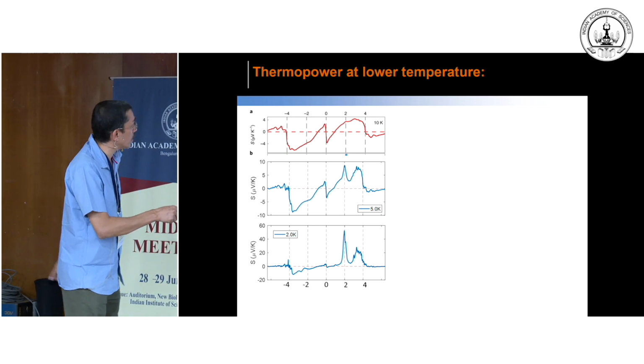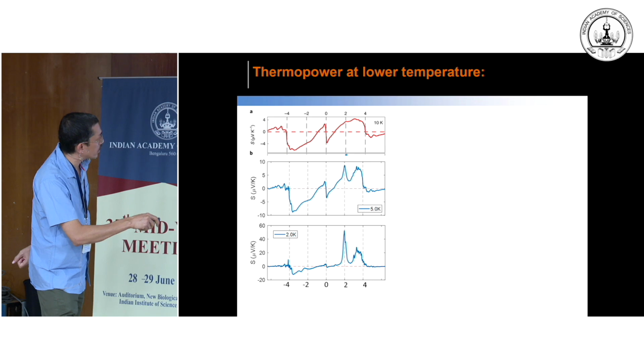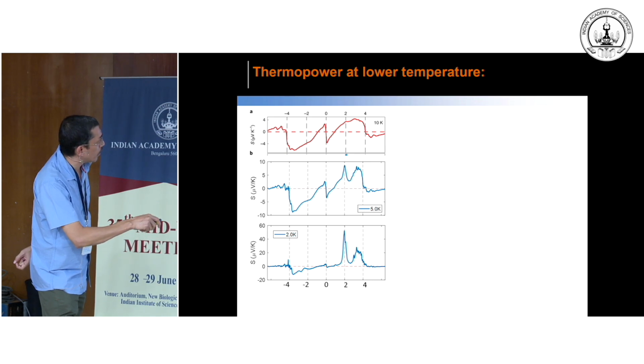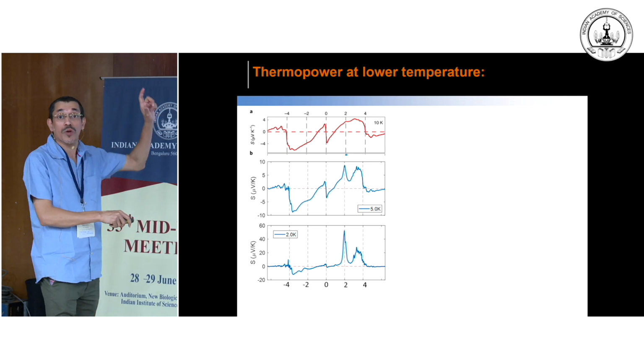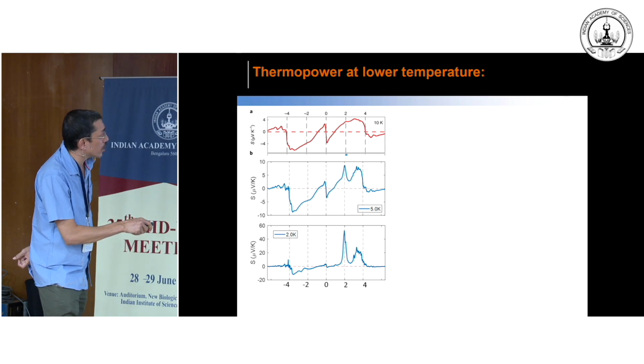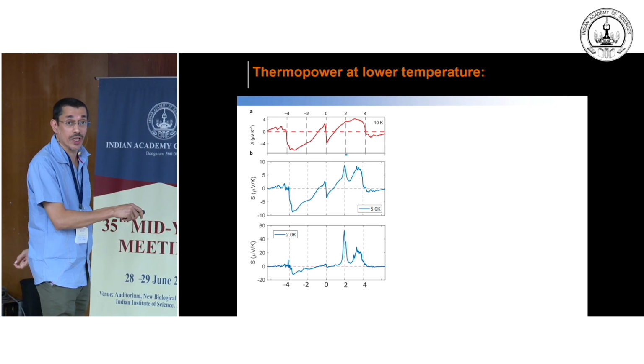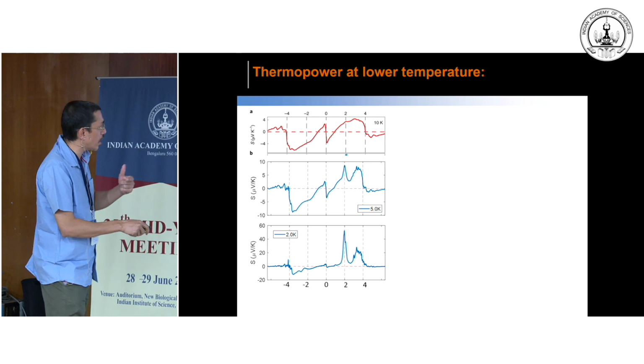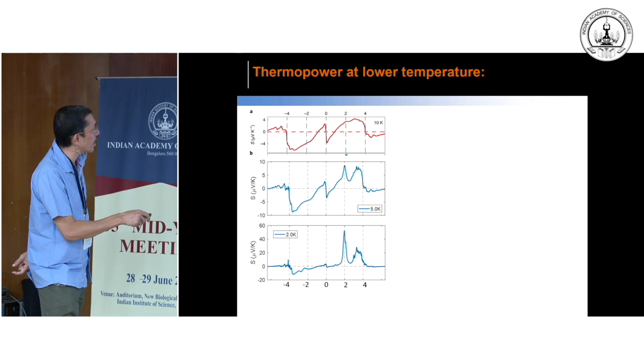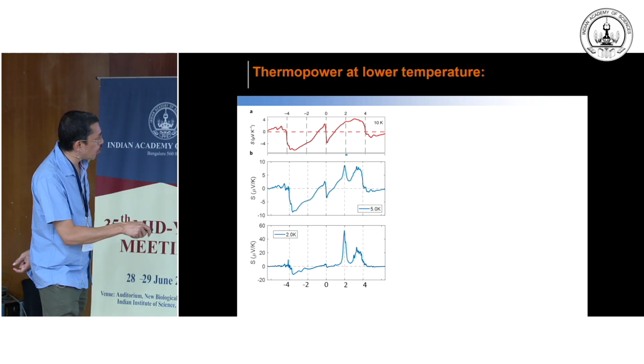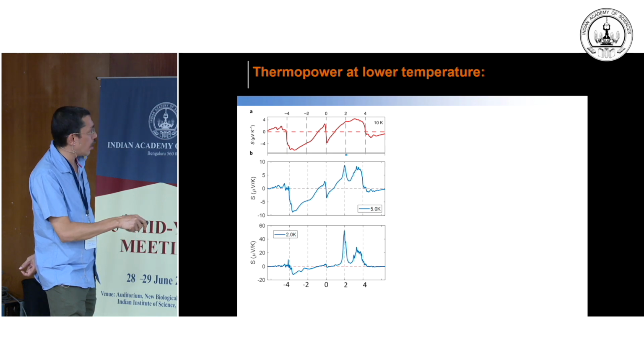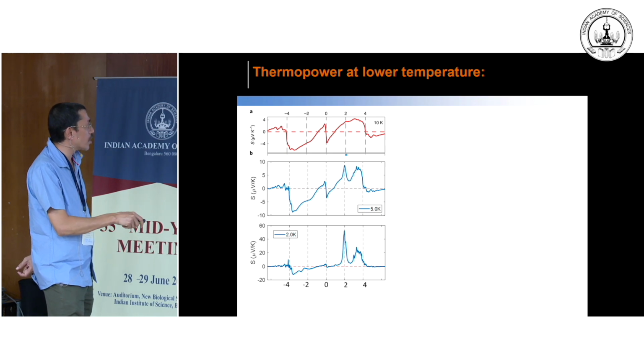One of the things is that if you lower the temperature, you can see the thermopower at the integer filling. This is filling 2 electrons per moiré unit cell. Thermopower actually gives you some kind of peak structure. This is unusual. You cannot explain it; I'll tell you in a moment why. As you lower the temperature even below 5 Kelvin, this peak becomes stronger.